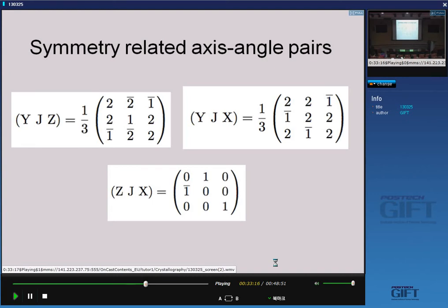If I take the angle of rotation here, then this plus this plus this is equal to 1 plus 2 cos theta, and therefore theta is 90 degrees. Because 1 is equal to 1 plus 2 cos theta, so 2 cos theta is 0, and therefore theta is 90 degrees. So it's a rotation of 90 degrees. And if you work it out, this is a rotation of 90 degrees about 0, 0, 1, the cube edge. And therefore, that's a symmetry operation, and therefore sigma is 1.